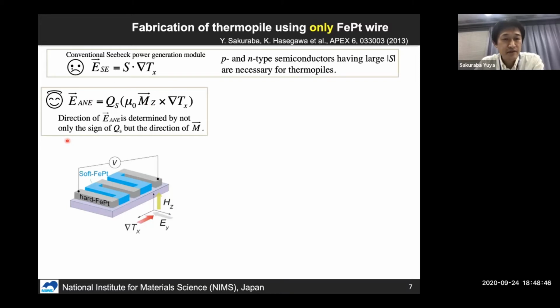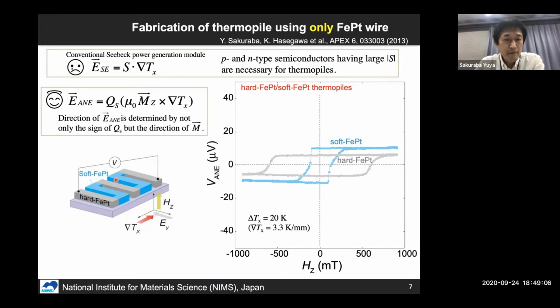As a demonstration, previously we fabricated this kind of anomalous Nernst thermopile structure using only iron platinum. But by changing the deposition condition of iron platinum, we make the iron platinum harder and softer. By measuring this hard and soft iron platinum separately, as you can see, this figure shows the anomalous Nernst voltage as a function of external magnetic field. We can clearly see the difference of coercivity in these two iron platinum wires.